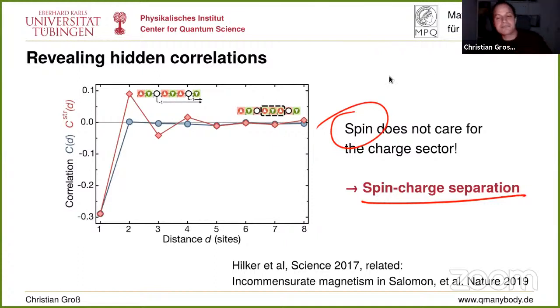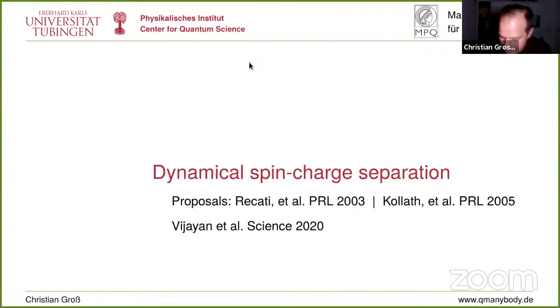Okay, good. So let me jump to the next part. The next part is my little excursion away from equilibrium, and it connects to the story of spin charge separation that I was just telling you we detected by correlations. These cold atom experiments are nice in the sense that the dynamics is slow, so you can follow the dynamics in real time. This is what we do now to uncover spin charge separation, really as a separation of wavefronts of the spin and the charge excitation. And that is following those two proposals here, both from Willi Zwerger's group.